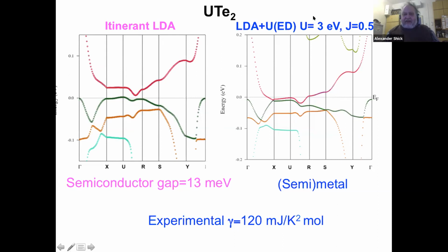And we took a moderate U, which is kind of common for uranium. We took 3 volts, while we could take 2.5 or 3.5. We didn't really calculate it ab initio. So this is the usual believable value of the Coulomb interaction on uranium. And J is half a volt, which is also a conventional number. And then we got it semi-metallic. So this gap is closed.